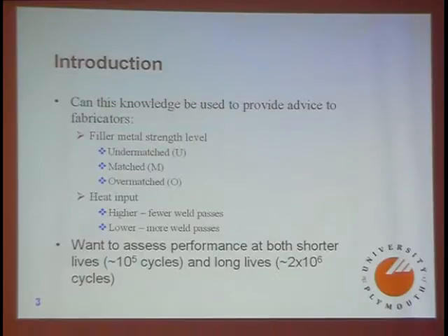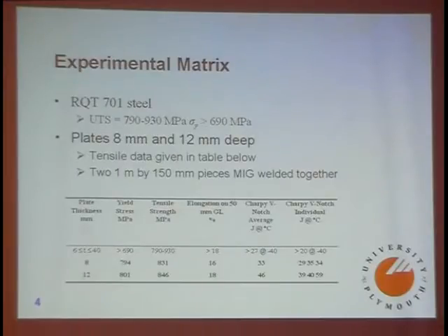Although this isn't taken account of in the fatigue design codes for welds, you often find there's a crossover in performance for two welds, nominally similar. And so it's worthwhile assessing life at shorter life, about 10 to the 5 cycles, and at lives longer than 2 by 10 to the 6. And you have another difficulty, of course, with longer lives in doing all the experiments that will establish the long life region adequately. Everything has a cost, as Maurice Sonsino noted yesterday, and these costs are often just too high for relatively small research projects. So this is a roller quenched and tempered steel.